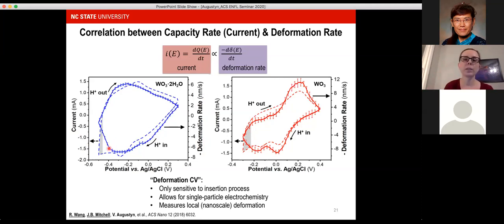We think this is a really interesting technique to apply for something like single particle electrochemistry and measurement of local nanoscale deformation if you're interested in the heterogeneity of the deformation across the surface of an electrode. So this was our clue that mechanics or structural changes were different between the two materials, something that we weren't able to capture the dynamics of that process using ex situ X-ray diffraction.